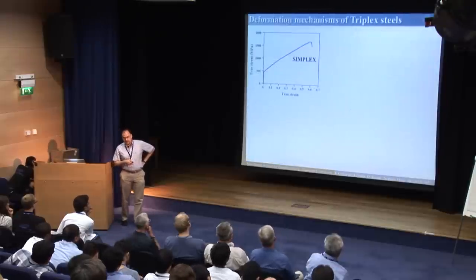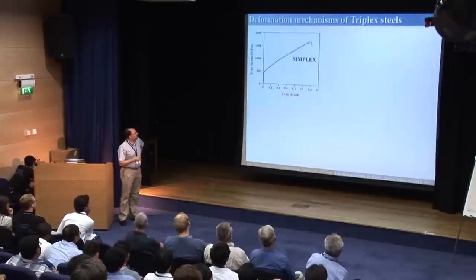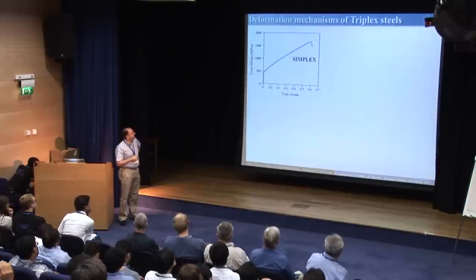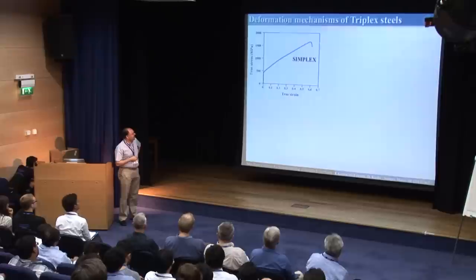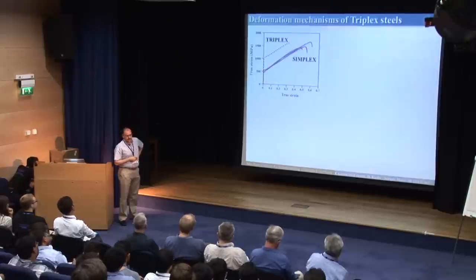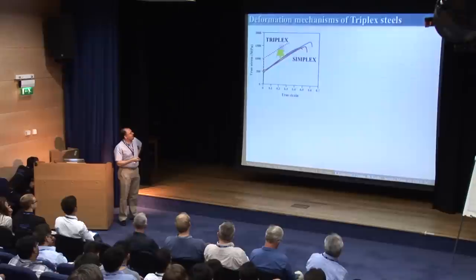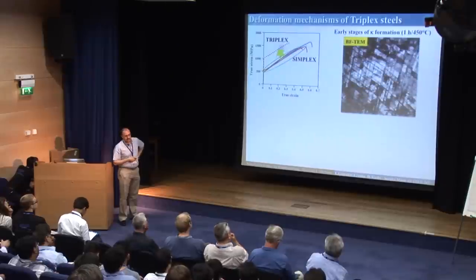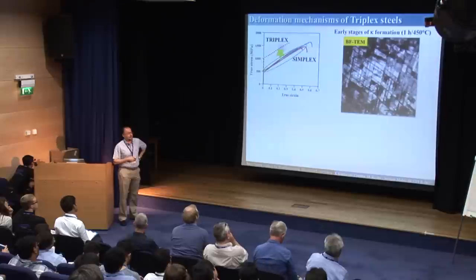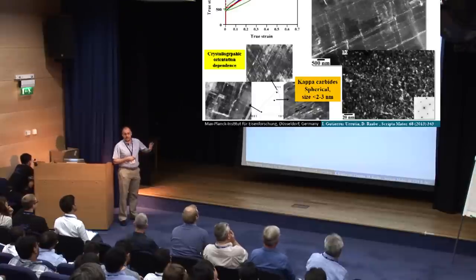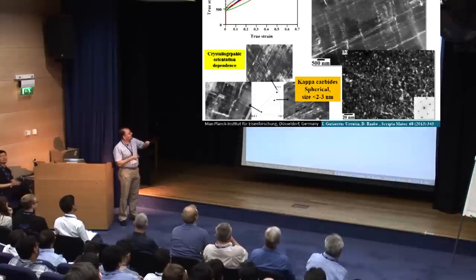Deformation mechanisms of these materials. So this is a uniaxial stress strain curve for a simplex steel. If we use this triplex alloys, well, if we only anneal below the formation of these kappa phases, it's very interesting because the dislocation structure is completely different to that revealed by the simplex alloys.